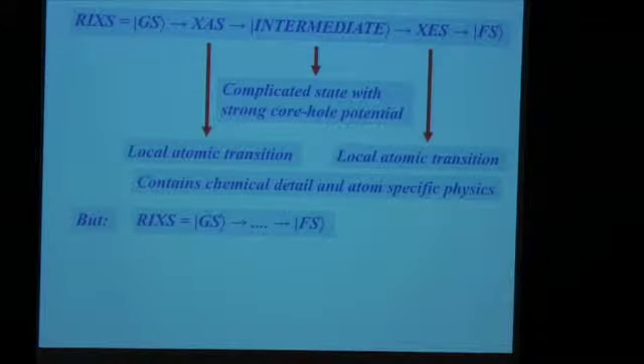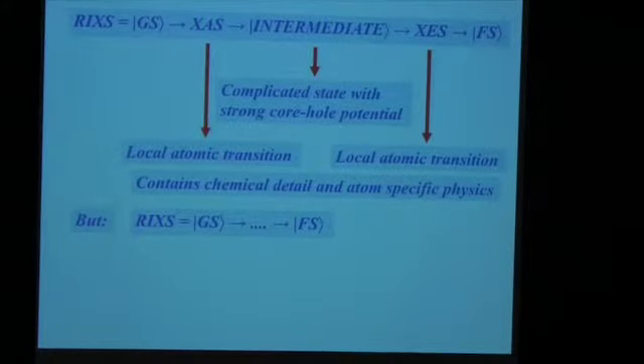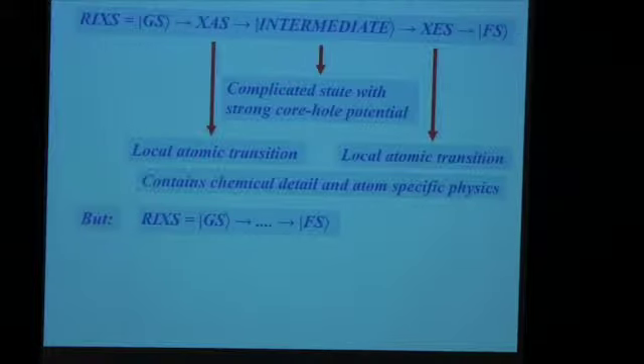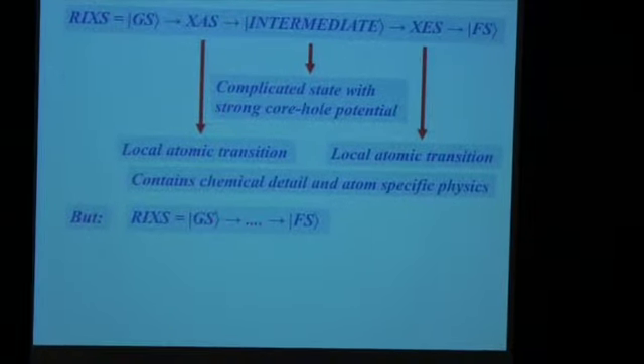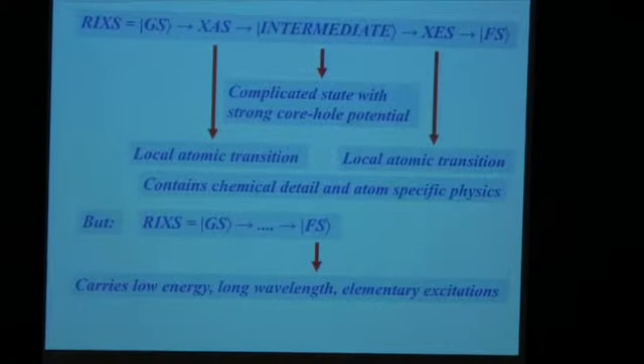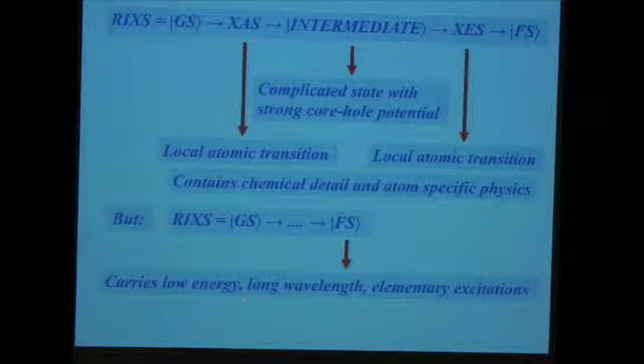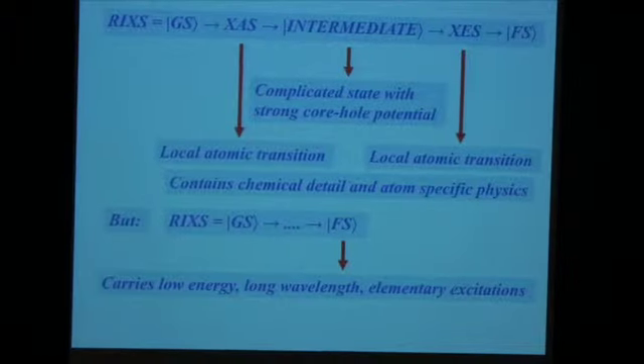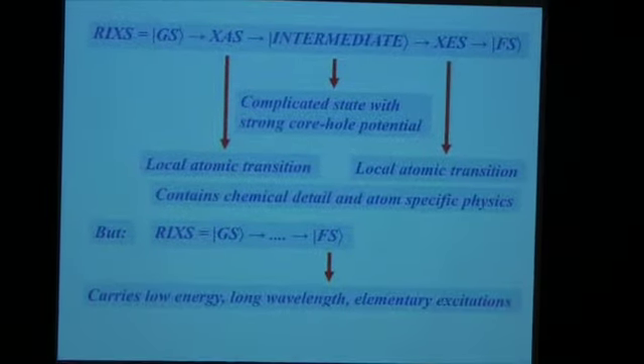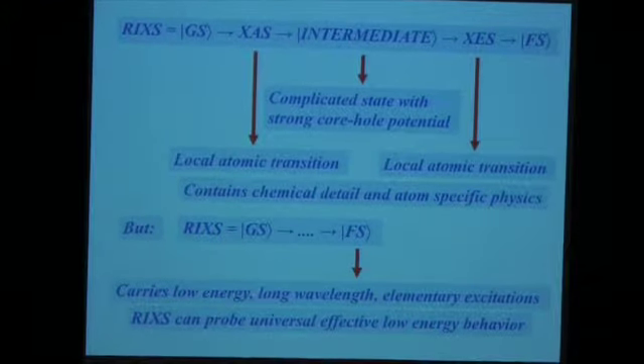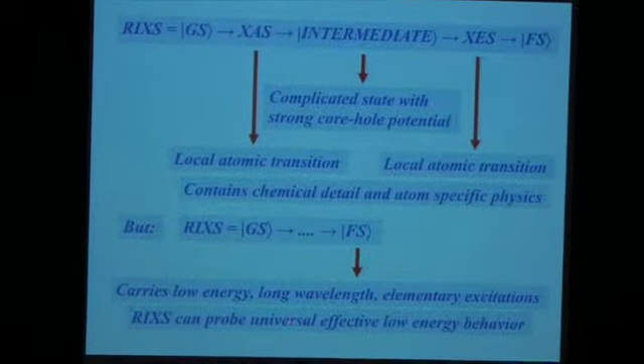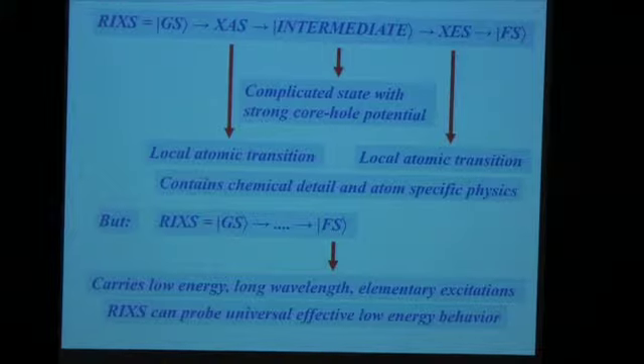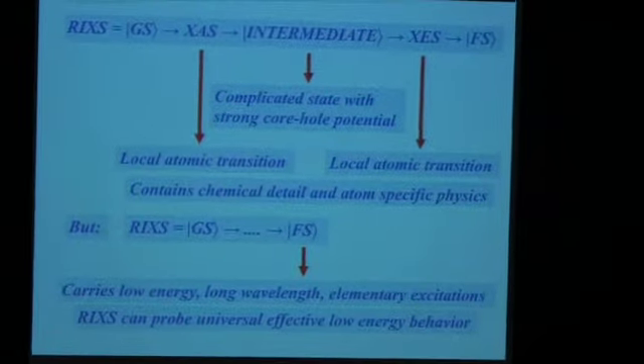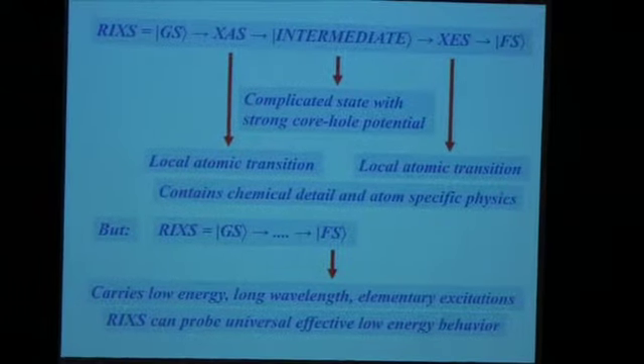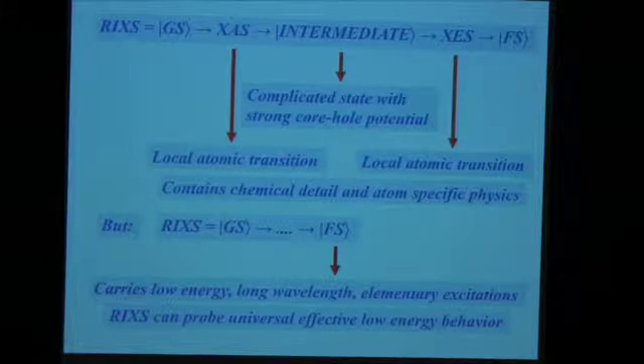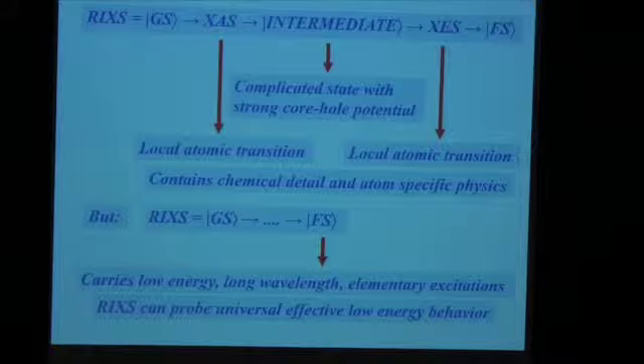However, there's the following argument, which now in hindsight is easy to make, but 10 years ago, people did not consider it at all. In the end, RIXS brings you from a ground state to a final state. This final state is only slightly perturbed. It carries the low energy, long wavelength, elementary excitations of the solid. Wild things can happen in between. I don't care really about it. I can learn about the low energy, long wavelength excitations, which means that RIXS can probe universal effective low energy behavior, at least in principle. X-ray absorption cannot, because in X-ray absorption you have a final state with a strong core hole potential which has perturbed your system way beyond a small perturbation of the ground state.